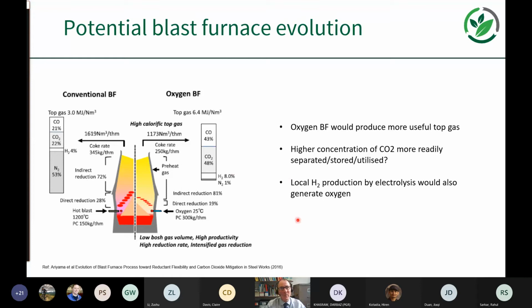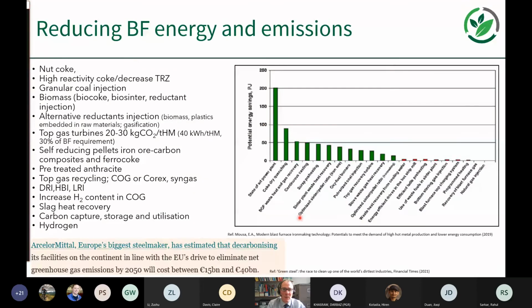And potentially, if we're talking about hydrogen in the blast furnace, then hydrogen production by electrolysis would also generate oxygen. So it could perhaps be synergistic to this kind of development of a blast furnace to a higher oxygen blast furnace. So there's quite a list of potential ways to reduce blast furnace energy and emissions, and quite significant savings associated with a state-of-the-art power plant, and coke dry quenching instead of the wet quenching that continues at the moment.